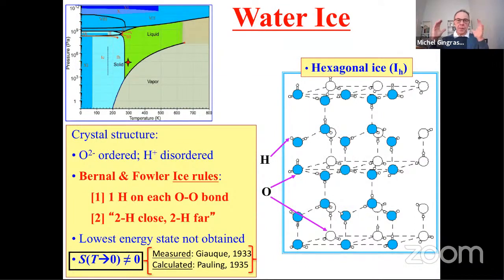The oxygen form a periodic crystalline structure, which is hexagonal, but the protons themselves are not ordered. The protons do not form a periodic crystalline structure. So water is a kind of hybrid between a crystalline structure and an amorphous state of matter, but it's not a glass. A glass would have a proton configuration which would be random. The protons are not random. They obey a very tight rule, the second Bernal-Fowler ice rule. So it's a very constrained type of amorphous structure.